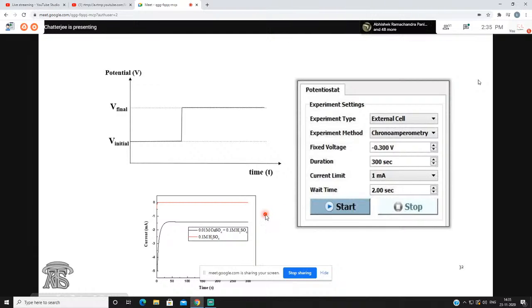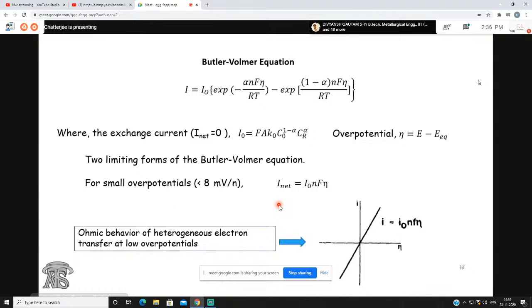Okay. So here it is only for the blank, the red one. I didn't take copper here, and there in presence of copper, copper deposition is taking place because we are getting some amount of current. The current has increased, the negative current. That is a reduction process, because I have told you that negative current corresponds to a reduction process. So here we can see this is the typical chronoamperometric response for the electrodeposition process. The Butler-Volmer equation already has been explained.